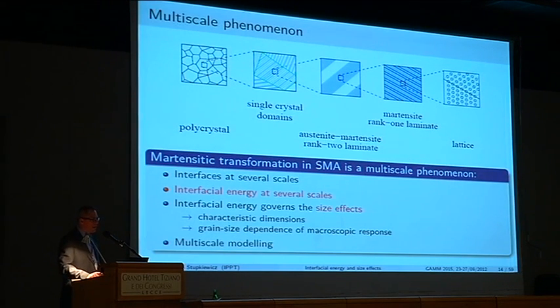So if we look again at the whole chain of modeling that you would have to apply to model these materials, we see immediately that this is a multi-scale phenomenon. You can distinguish several scales. If you want to model the response of a polycrystalline material, you have to consider domains, maybe in the grain, then laminates, and then sublaminates, etc., down to the atomic scale. So there is, of course, a need for multiscale modeling.